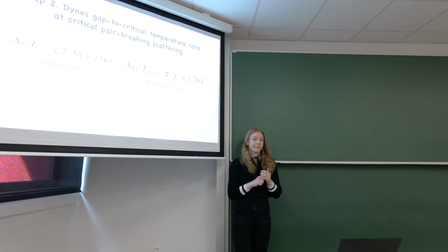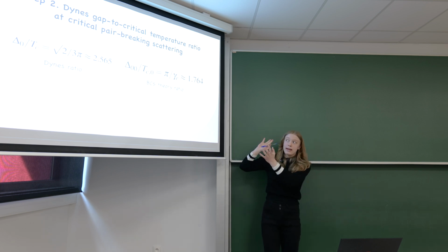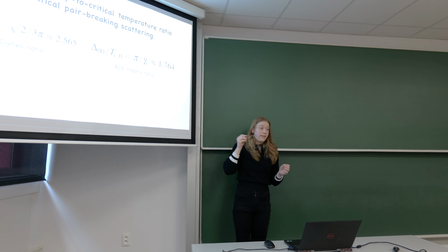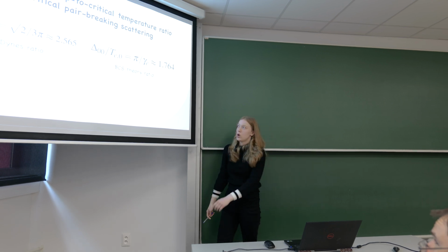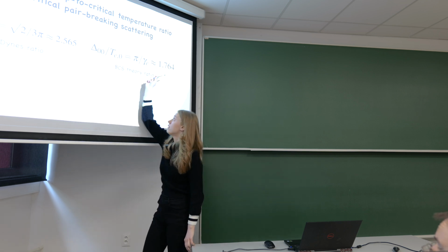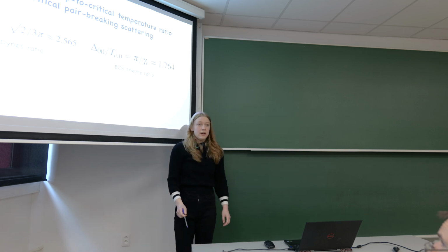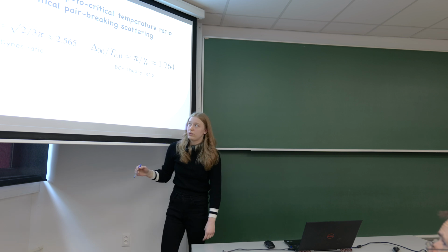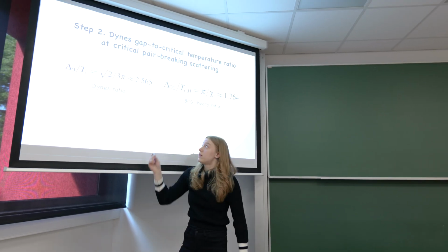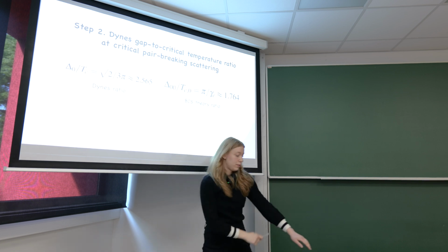Okay, now let us compare these two values to find out how pair breaking affects superconductivity. We see that this ratio is higher than this ratio, which means that at critical pair breaking scattering, the critical temperature is suppressed to 0 a bit more than the energy gap.